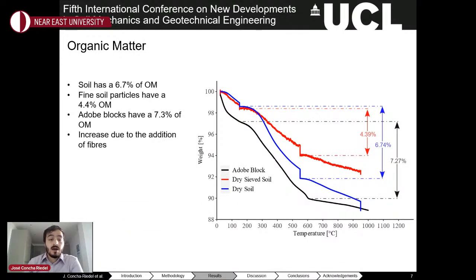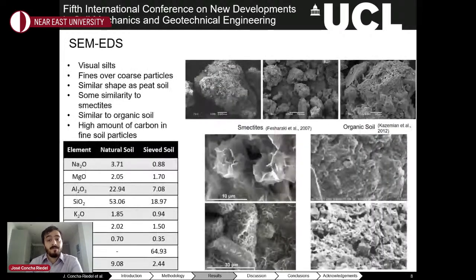For the organic content, a thermogravimetric analysis was used. This test was performed on the soil sample, the fines obtained through sieving, and on an adobe block sample. Typically, the range at which organic particles are burned is between 100 and 600 degrees. With this, we obtained that the soil has 6.7% of organic matter, the fine particles 4.4%, and the adobe blocks 7.3%. The increase of the organic matter in the adobe blocks could be related to the inclusion of fibers. However, further research must be conducted to address this point.